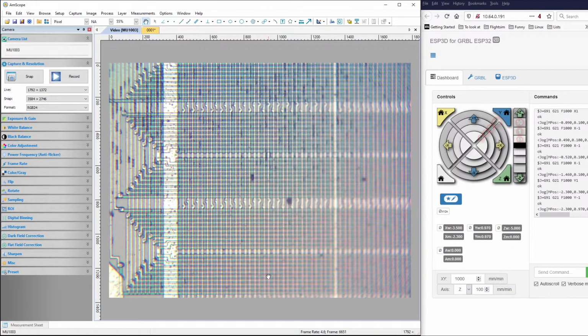So I think that's pretty much it as far as image capture goes. When it comes to decapping chips, there are many methods of doing this. The most commonly used, I would say, among professionals is using acids to etch away the epoxy, because the chip encapsulation is made out of this really hard epoxy. And ultimately, the IC inside is just a small bit of glass. It's fairly fragile. It's not horribly fragile, but you can't just crack the chip open as is, because you will also crack the die.